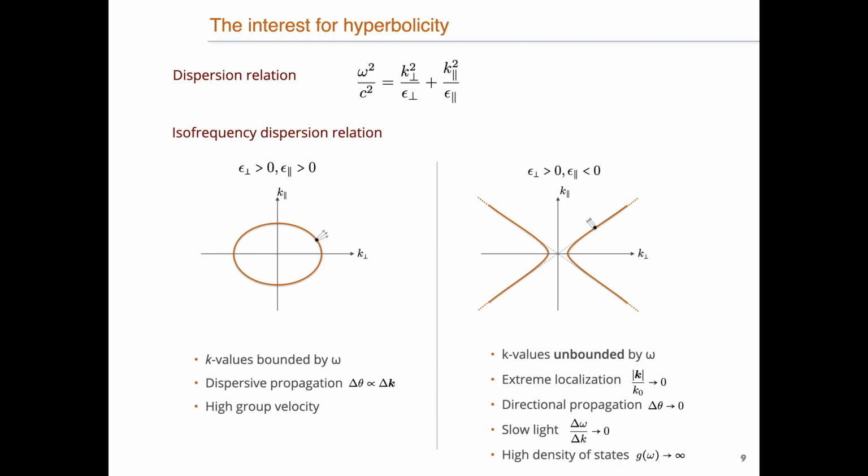The confinement factor is calculated using k in free space and the k that is achieved in the material. So if the wavelength in the material gets much smaller, the confinement factor can be as high as about 100. Okay, so that's the maximum that can be achieved. What wavelengths does that correspond to?